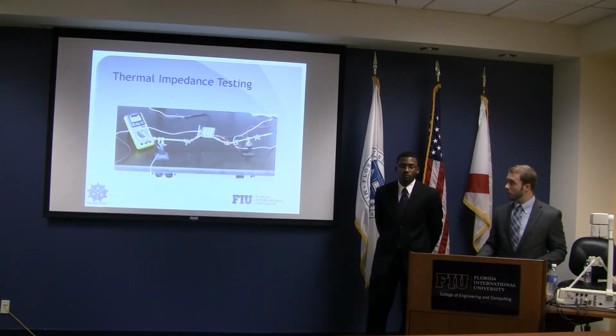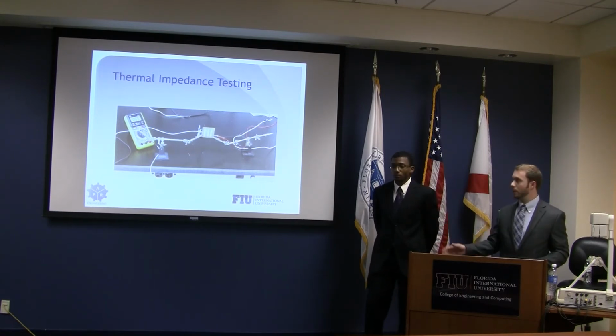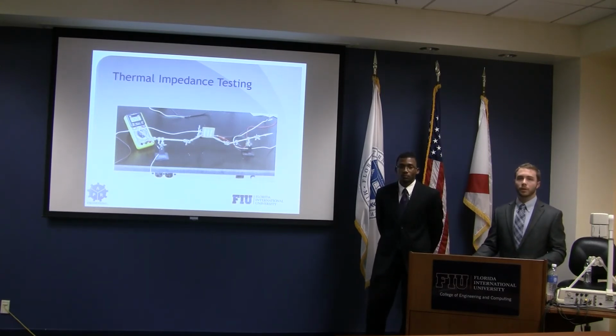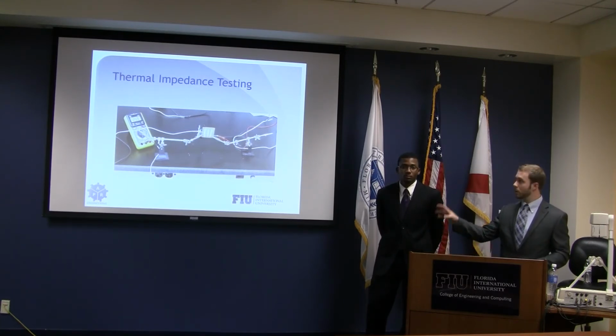And as you see, this board is the regolith board. We also use the DuPont 951 board as well, same configuration. Essentially what we did is we had a grid on this that was 5 by 8, so we had testing points at 40 different locations within that silver area.